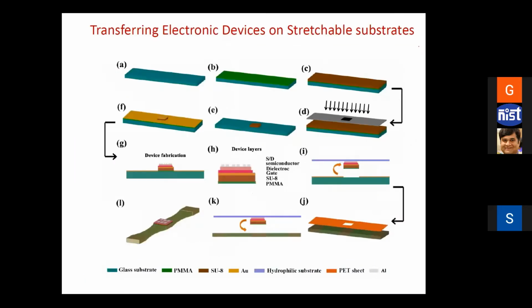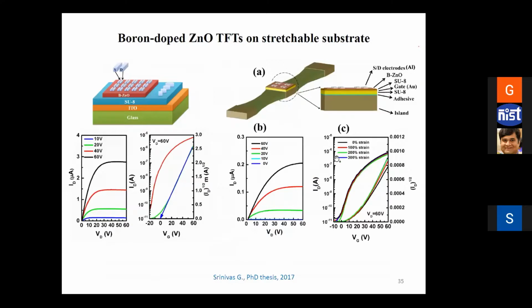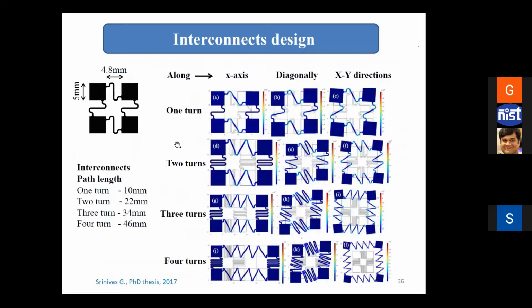Then we tried to come up with some recipes so that we can transfer the transistors that we fabricate onto these stretchable substrates. These are a few devices where we show that even at 300% strain, the device properties do not change. And these are a few interconnect designs we came up with. For example, this portion over here has a spiral kind of design. We call it 1 turn, 2 turns, 3 turns, 4 turns, right? So you don't interconnect this device with a straight line, but try to convert it into a spring-like structure, such that when you stretch it, this interconnect does not break.